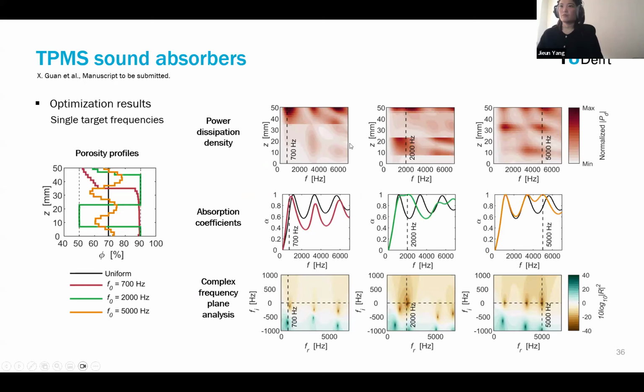So to understand that, we first conducted single target frequency optimization. So these are the results. Porosity profiles for the single target frequencies 700 Hz, 2000 Hz and 5000 Hz. So what we wanted to do here is to optimize the sound absorption coefficient just below the first sound absorption peak, and also the frequency in between these two absorption peaks, and also the one in between the second and third sound absorption peaks. So for the first one, 700 Hz, you see that the porosity on the top layers have lower values, and when you get into the bottom side of the porous layer, they have higher porosity at 90%.